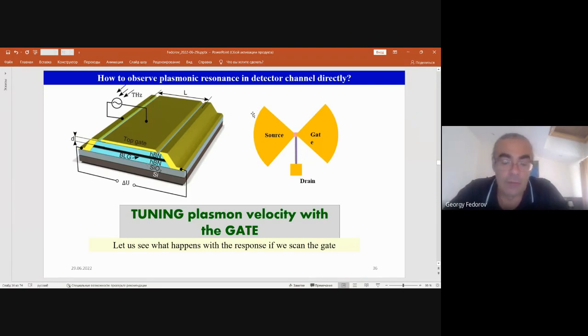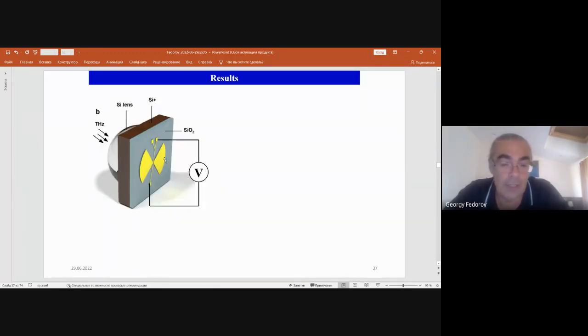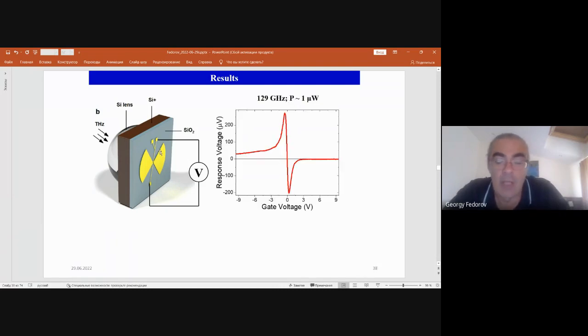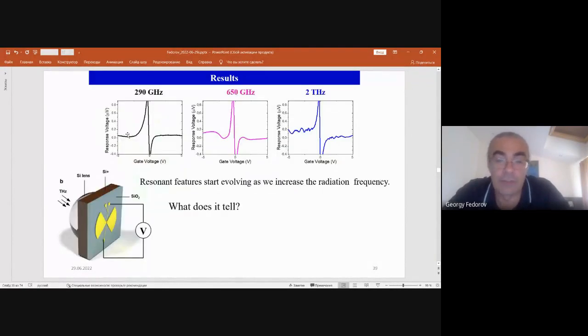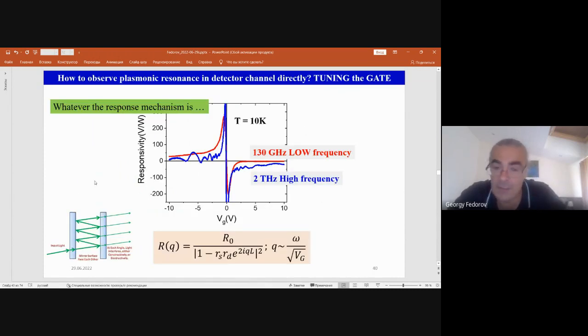And then we use a standard antenna to couple the radiation between source and gate electrode, and we measure the voltage between source and drain. And as we scan the gate voltage, first at a lower frequency of radiation, we see nothing special. But as we increase the frequency of incident radiation, we see some oscillation-type features evolving. So what does it tell? It tells us that we did make a Fabry-Perot interferometer.